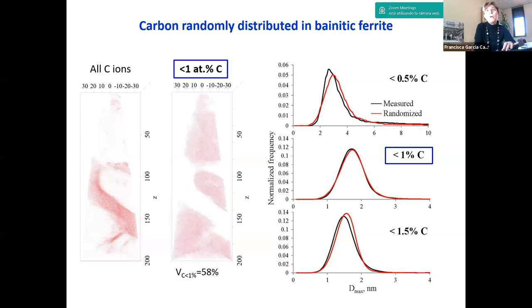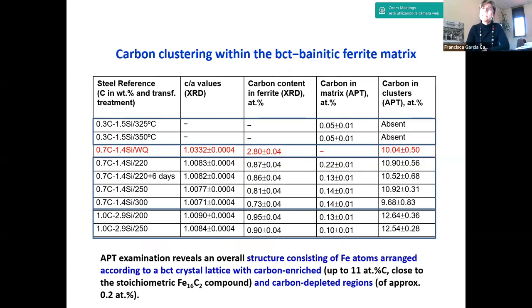Let me show you the evolution of the carbon supersaturation related to tetragonality and carbon clustering in bainitic structures transformed at different temperatures, in relation to martensite, in this case as-quenched martensite. In red is the as-quenched martensite, in black are different bainitic structures: medium carbon high silicon steel transformed at intermediate temperatures, and high carbon high silicon steel transformed at low temperature. In one case, we have an evolution of time here. In the first column, this is the tetragonality measured by X-ray analysis. And again, we cannot say the level of tetragonality we are dealing with in low temperature bainite is comparable to as-quenched martensite. In the second column, this is the carbon content according to X-ray analysis.